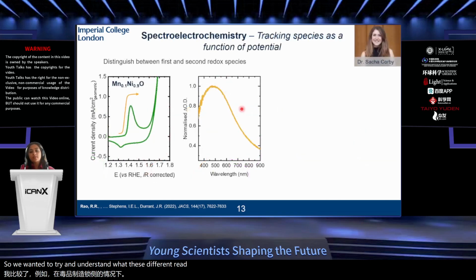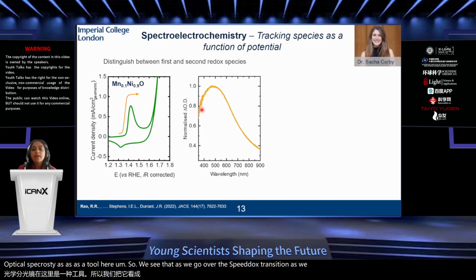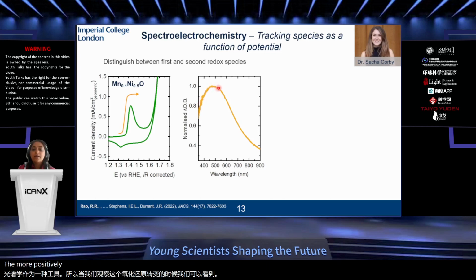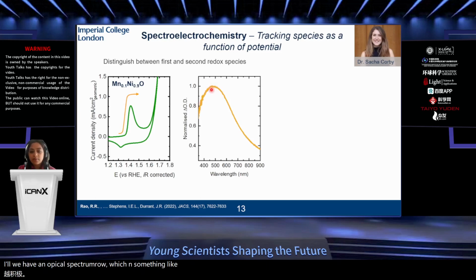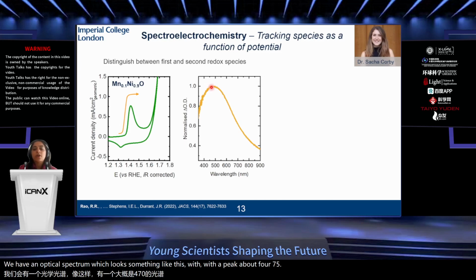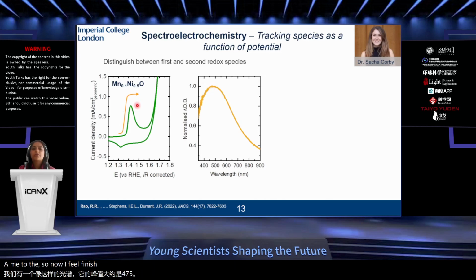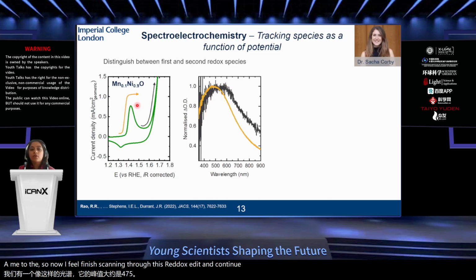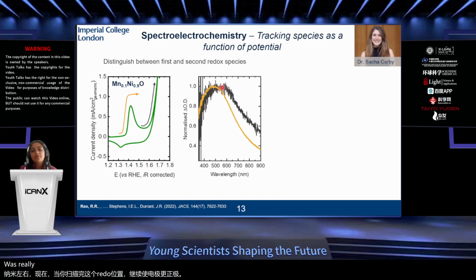So we want to try and understand what these different redox transitions are, and we can do that by looking at optical spectroscopy as a tool here. So we see that as we go over this redox transition, as we scan the potential more positively, we have an optical spectra which looks something like this, with a peak at about 475 nanometers or so. Now, as you finish scanning through this redox transition and continue polarizing your electrode more positively, what's really interesting is we see the evolution of a different spectral feature which absorbs at slightly larger wavelengths.